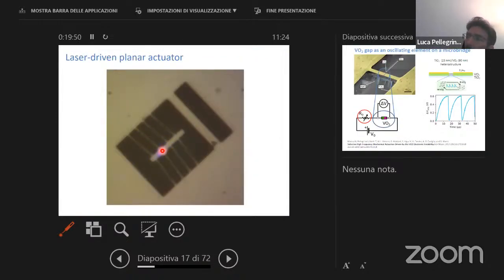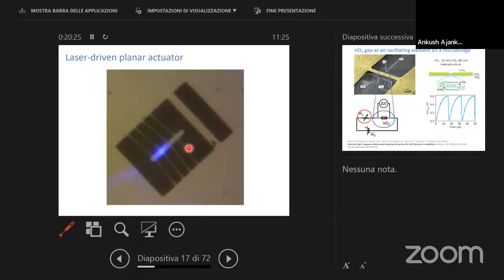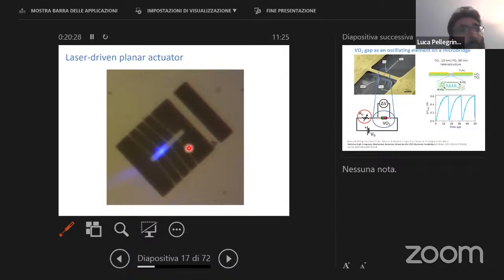This is a blue laser heating the sample. So you go with the laser, you heat up the sample, heat is diffusing across the sample leg here. You are increasing, and then you are moving the sample. And just want to say that if this sample was a normal material, this would not move like this, because in these small temperature windows, the change of the strain on our sample is quite large, which is tens of %, which is quite large for systems. If you use gold, for example, a gold structure would change very little, because the thermal expansion in 5-10 degrees is a very small value.